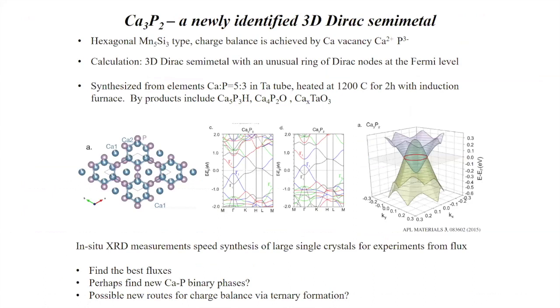So I'm going to start off by giving you a simple example of why this works so well for us. At a certain time, we had the idea that we might want to grow this material, calcium-3 phosphorus-2. It was an interesting 3D Dirac semi-metal. And at the time, the samples were being grown in essentially a solid-state synthesis approach by just putting the right amount of calcium and phosphorus into a tantalum tube, heating it, and then cooling it down. The problem with that is that the crystals were very small, so that made the experiments super difficult, and many products were produced in the tube, meaning that the synthesis wasn't particularly efficient.